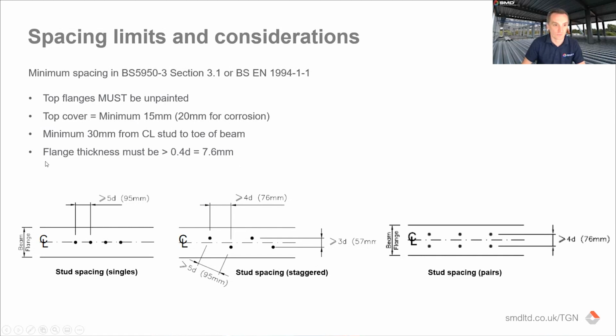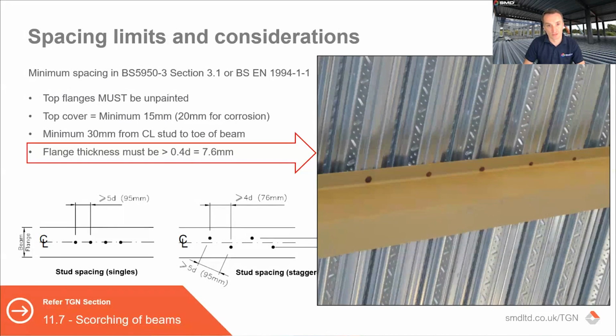And the key one to make note of is that the flange thickness must be greater than 0.4 times the diameter of the stud, which for 19 millimeters is 7.6 millimeters. But an important thing to realise is, if you're designing at the very lowest thickness of a flange, due to the temperatures involved in the weld process, you may end up with damage to the underside of the beam, to repair or make good or be touched up later. So it's an important consideration, and as you can see, 11.7 in the TGN gives you a bit more info. You'll see this photo and a bit more on that subject.